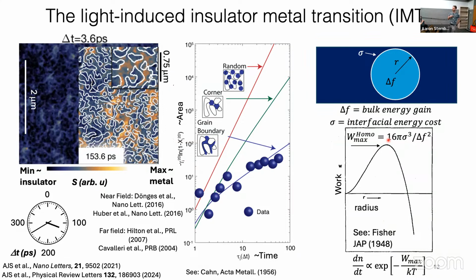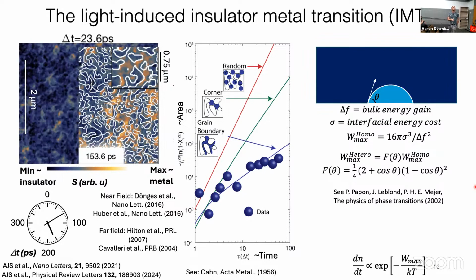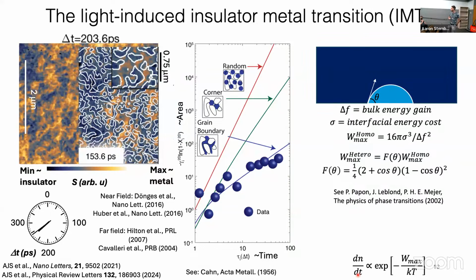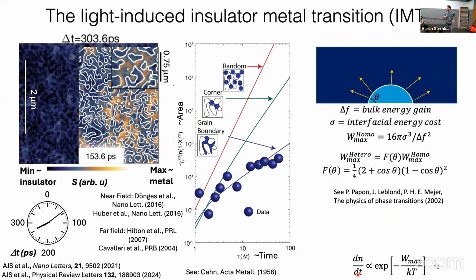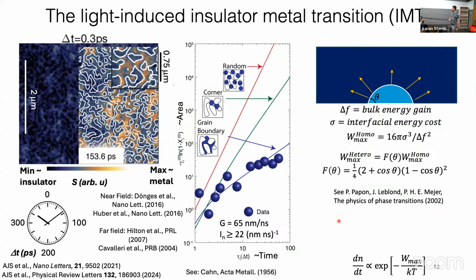Now, the system has a very nice natural way of speeding this process up if there are boundaries in the film, because the work barrier can be reduced by wetting. So if the metallic nucleus forms at a boundary, then the work is reduced and the system can nucleate metal faster. However, in this case, you still have to wait for the metallic domain to grow into the rest of the film. And from this data, we can extract a rate of growth and put a bound on the nucleation rate at a given fluence.